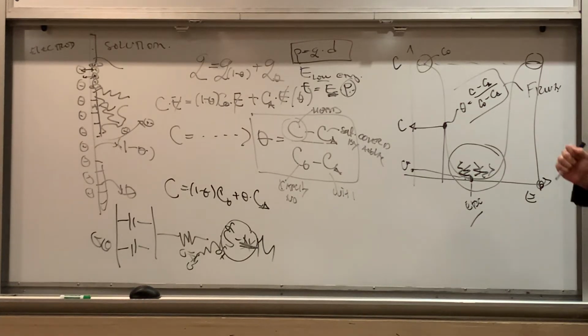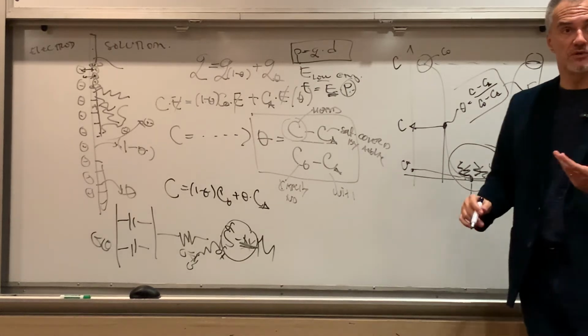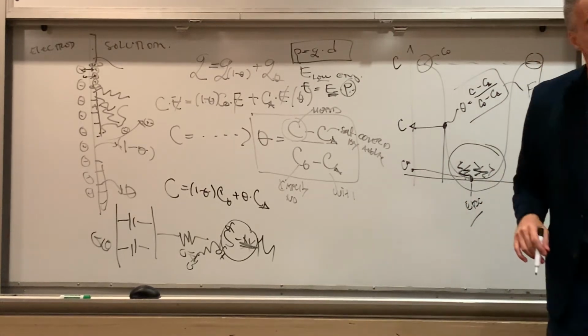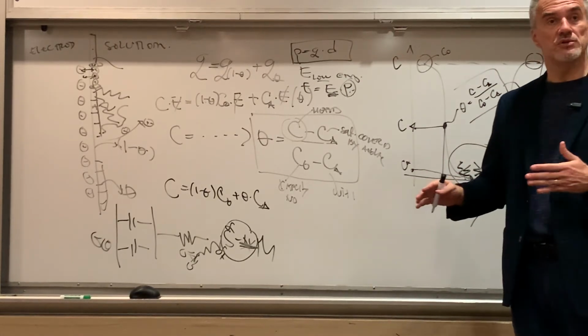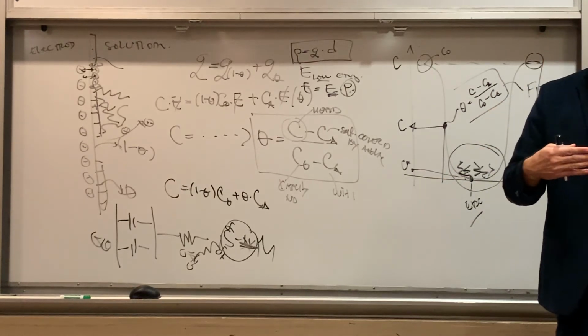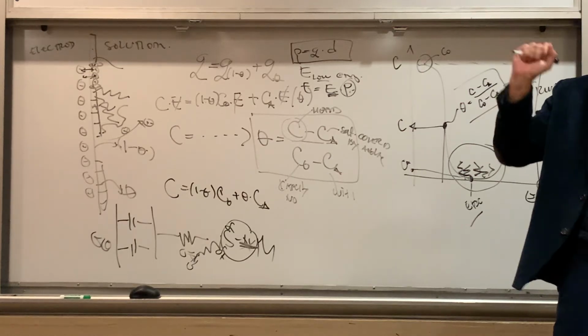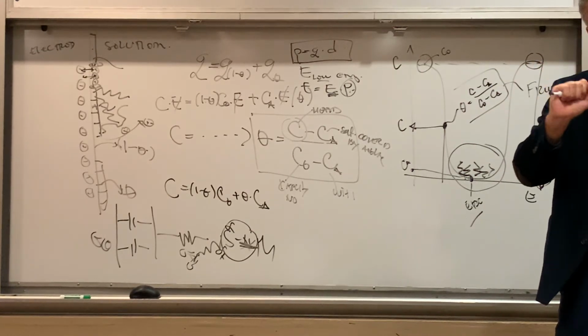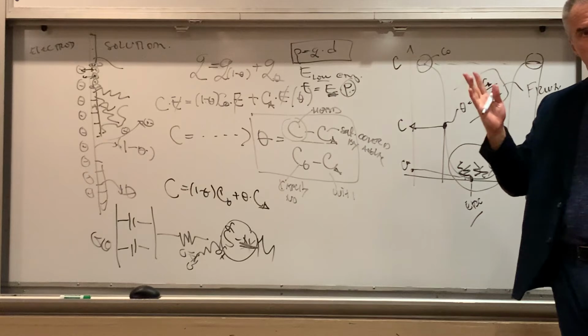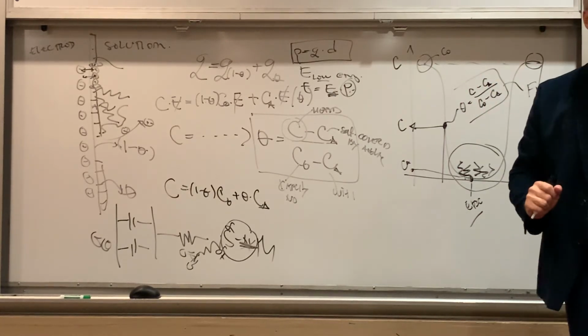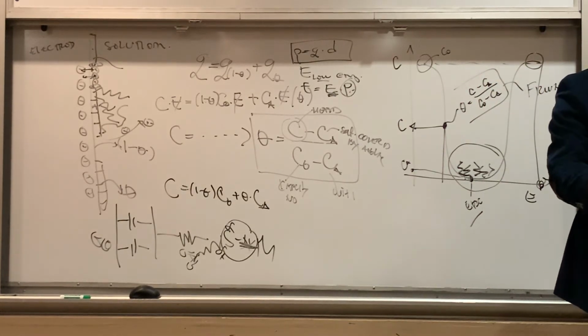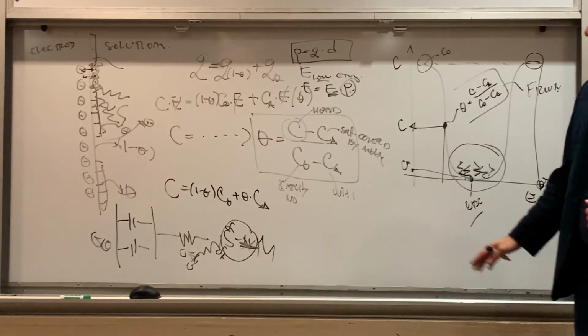Now, the logic to know where your additive adsorbs is to first know where your PZC is. And your PZC you can always determine for your electrode by studying capacity as a function of the potential in a low concentration electrolyte. And then you get this. Then you know where the approximate PZC is. Then you can start adding your additives. You're going to see immediately that they will be adsorbing in that region there.